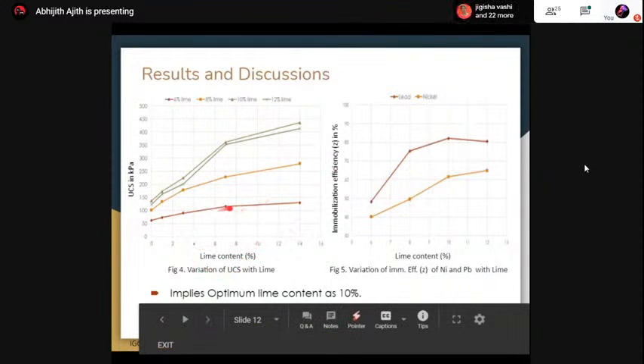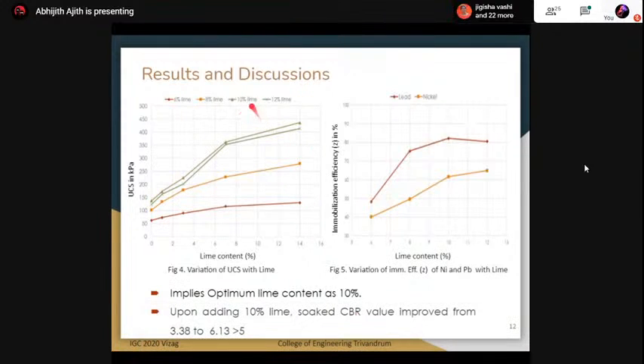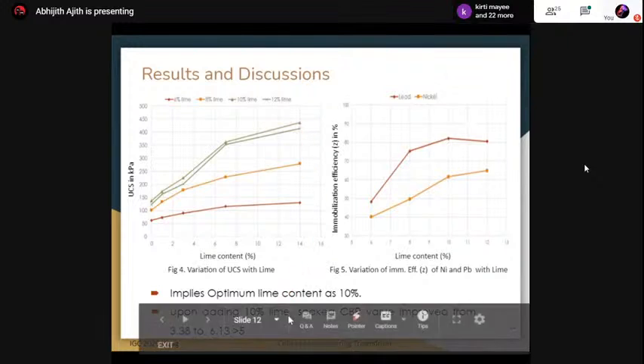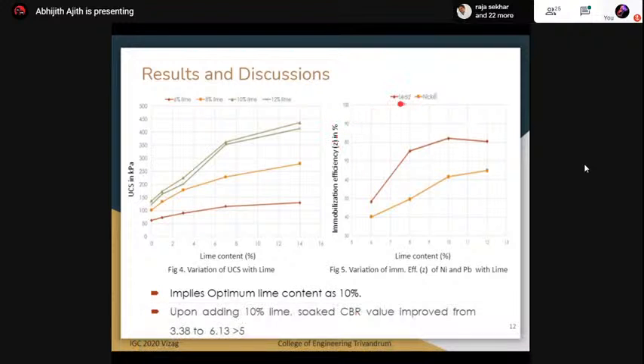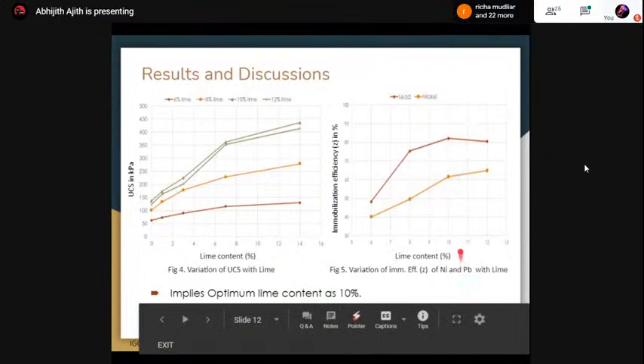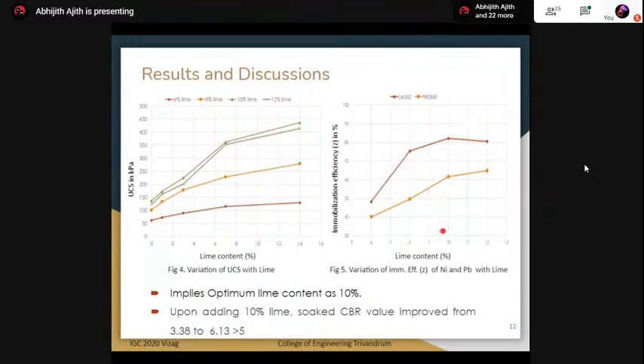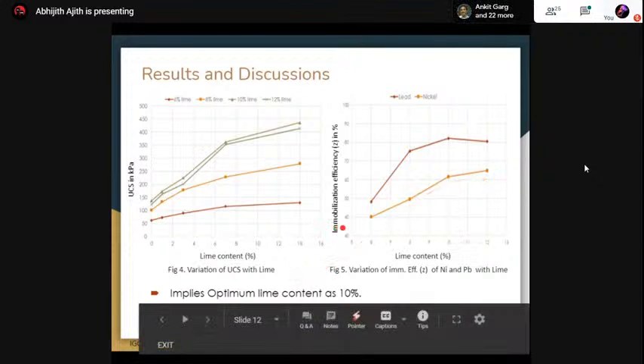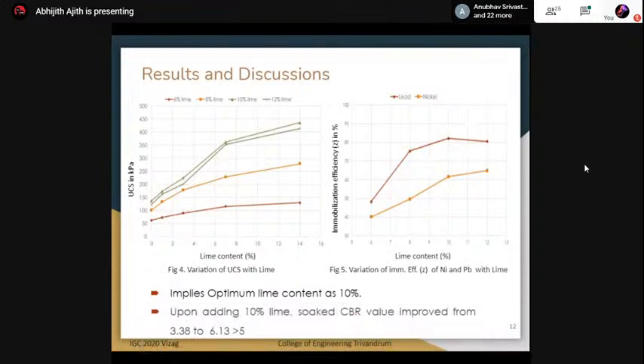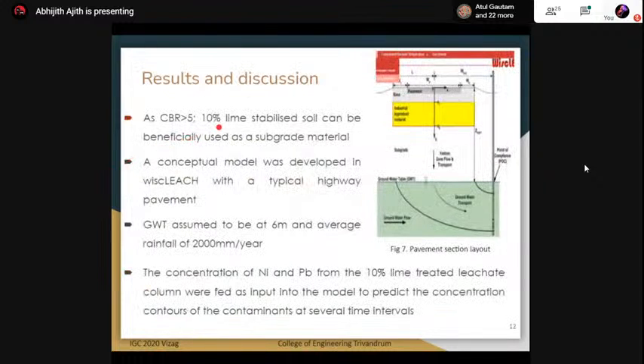Now, moving on to the UCS samples. As lime is increased, the unconfined strength was also found to be increasing, but 10% lime had the maximum, thereby the optimum lime content is taken as 10%. When you also look at the immobilization efficiency of the contaminants, lead and nickel, for 10% the maximum efficiency was achieved at 82% for lead, whereas in the case of nickel, on further increase of lime content beyond 10%, the immobilization efficiency was also found to be increasing. It should be noted that the 10% lime mix also had a CBR improvement of about 6.13, which is greater than 5, thereby as per IRC, we can beneficially use it as subgrade material.